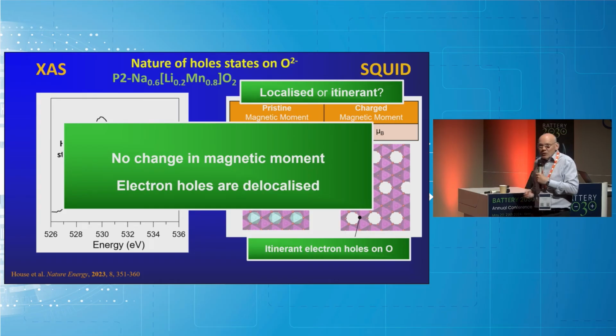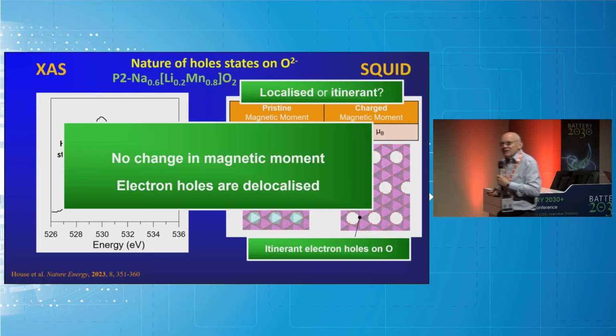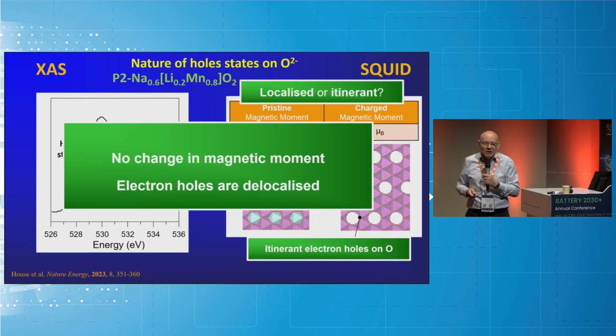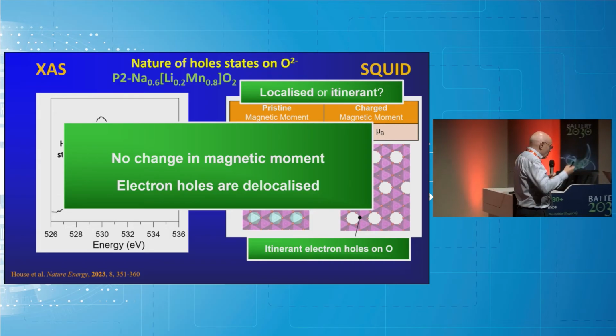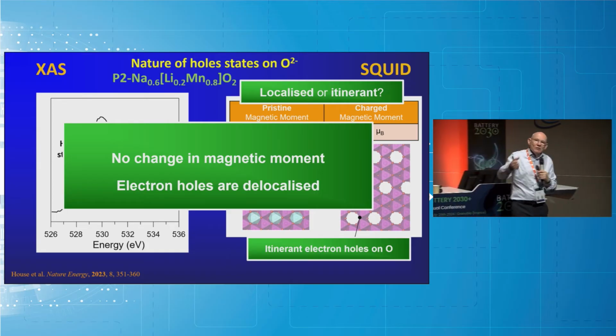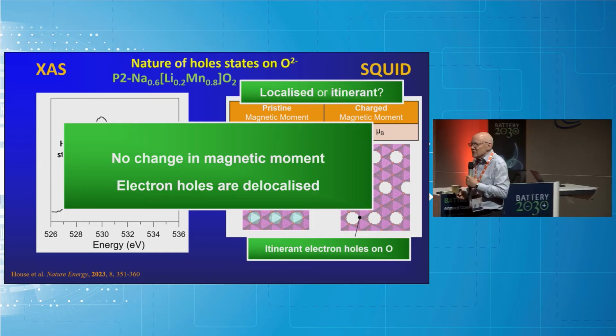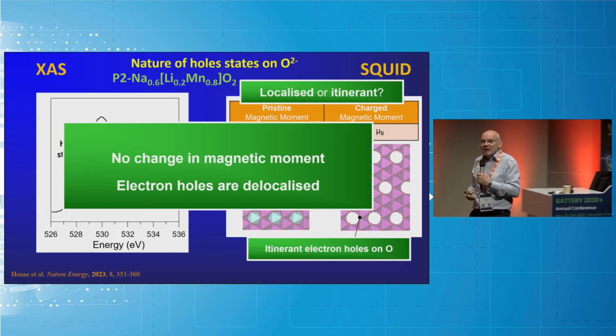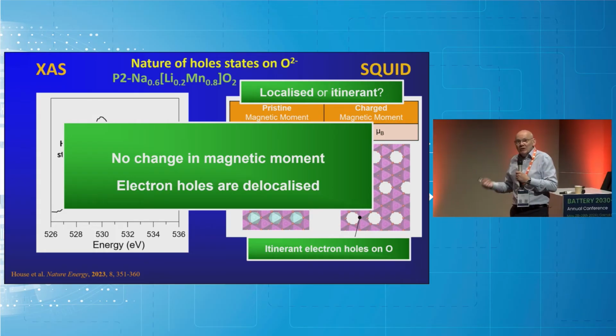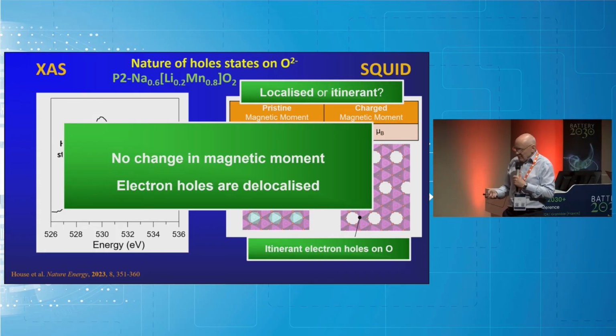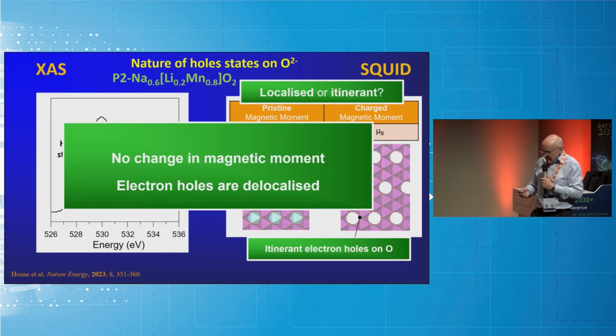And, of course, what you also understand from this is that these electrons are delocalized. The reason you see no change in the magnetic moment is, first of all, there's no molecular O2, so no unpaired spins. And the holes that you create are itinerant. You have delocalized electrons in the oxygen valence band, so they're Pauli paramagnetic.